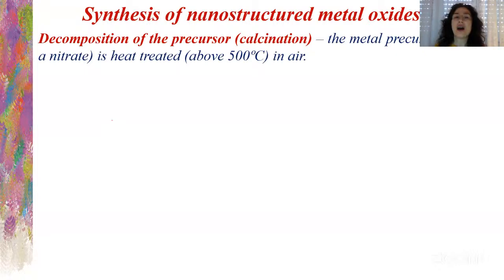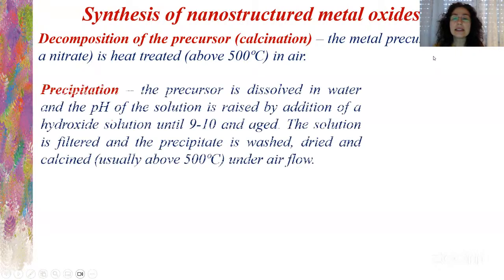The synthesis of nanostructured metal oxides can be done in several ways, and one of them is the decomposition of the precursor, therefore by calcination, for example. The metal precursor, usually a nitrate, is heat treated above 500 degrees in air. Another method is, for example, precipitation. The precursor is dissolved in water and the pH of the solution is raised by addition of a hydroxide solution, usually until a basic value of 9 or 10, and then it is aged, we let some time pass, usually some hours. The solution is then filtered and the precipitate is washed, because during that aging time there is precipitation.